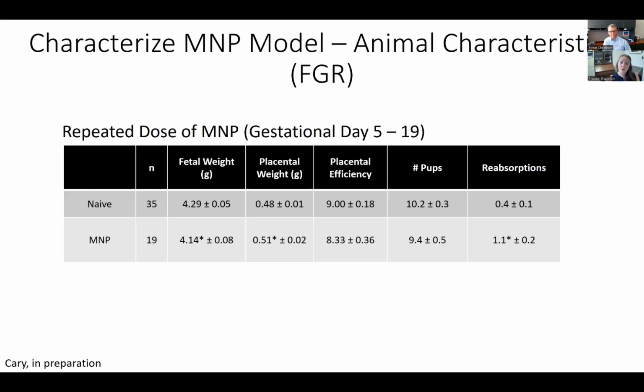We've moved that into our pregnancy model, and in those characterizations, we're able to see that we do get a fetal growth restriction phenotype after repeated exposure to our polyamide particles from early pregnancy, gestational day 5, all the way through gestational day 19. And these animals are sacrificed on gestational day 20. We see an increase in placental weight, which doesn't really correlate well with that fetal weight decrease. So that's a unique outcome for micronanoplastic exposure. We also see a reduction in the number of fetal pups, but that's not to significance, and it's likely associated with a significant increase in fetal reabsorption, and that's a miscarriage in a rodent model. So we do see some pregnancy outcomes.